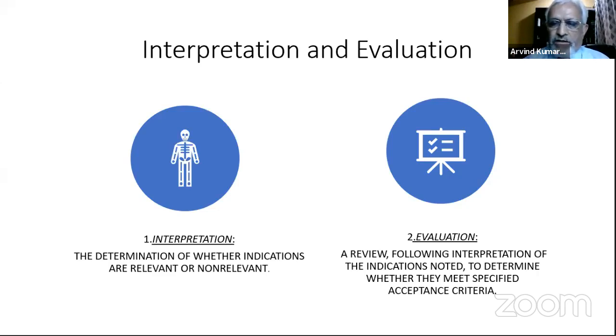So evaluation would be, once you have established that yes, it is a relevant indication, then you have to evaluate against your acceptance norms or against whatever code you are following, whether that relevant indication is meeting your requirement or not. And most of the codes, at least for penetrant testing and magnetic particle testing, will not accept any linear indication. So rounded indications like porosities, there are acceptance limits given, say a 5 mm isolated spot can be accepted and things like that. But linear indications in PT as well as MT are not acceptable.